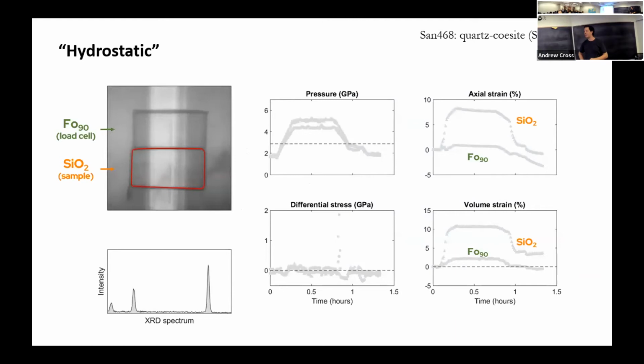So here's one hydrostatic experiment, at 900 degrees C for SiO2. You'll see that hydrostatic is in inverted commas here. The reason for that is the D-DIA doesn't compress and decompress perfectly hydrostatically. We do get some wiggle in the amount of differential stress that's being felt by the sample. So it's on the order of tens or maybe up to 100 or so MPa through the experiment, but still relatively small. When I play this movie, I'll probably play through it a couple of times.